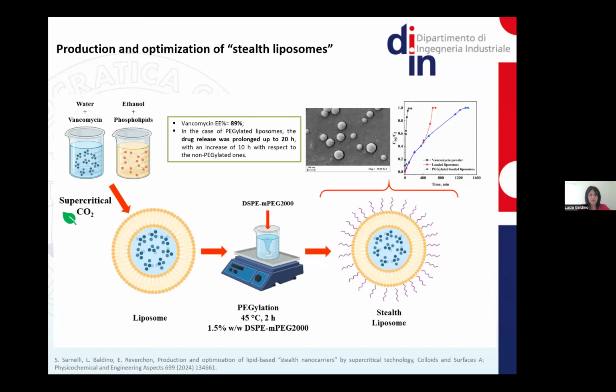characterized by a spherical, regular, nanometric mean dimension, around 200 nanometers. We achieved a vancomycin encapsulation efficiency up to 89%. And also we checked the vancomycin release time and profile from stealth liposomes. We obtained that in the case of stealth liposomes, we detect an increase in the release time up to 20 hours, with an increase of 10 hours with respect to the release from simple liposomes. So in this case, we also verify the mass transfer resistance opposed by the external coating of.